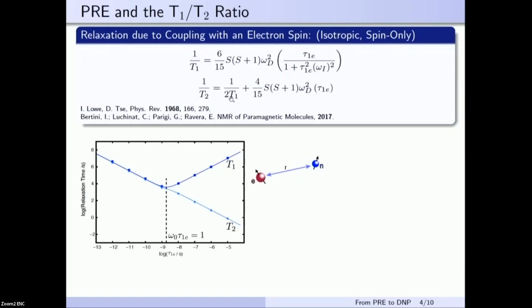Now, if we plot these two equations of the relaxation versus the correlation time, we get this very famous figure of NMR relaxation, where T1 passes through a minimum, while T2 keeps decreasing with increasing correlation time, so with slower motions. Now, how would this curve look if we increase the strength of the dipole coupling? Well, the curve will look exactly the same, just shifted down, so to shorter relaxation times. I want to draw your attention to the fact that the ratio of T1 over T2 has not changed between the two cases. It only depends on the correlation time, which in our case is the electron relaxation time. So the other way around, if we know the ratio of T1 over T2, we can obtain the electron relaxation time.